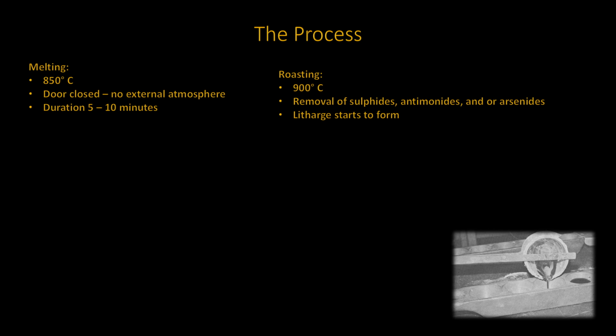After the initial 5 to 10 minutes, the outside air is allowed to slowly enter and the temperature raised to 900 degrees centigrade. This is the roasting stage. It is during this stage that any antimonides, arsenides, and sulfides are oxidized and expunged. Sulfides can be seen floating on top of the melt. The elemental lead will start to form lead oxide.